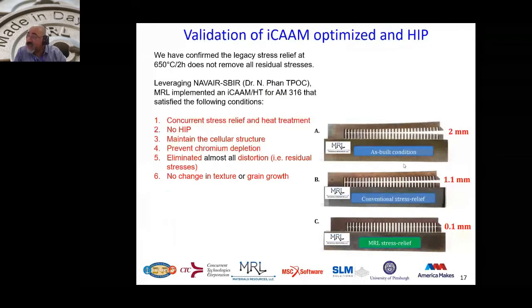What you will see in slide number 17 is comparing the as-built condition with the conventional stress relief process, and then with our stress relief approach. And you can see we wanted to demonstrate it in the standard cantilever. The heat treatment approach that we developed at MRL resulted in less than 0.1 millimeter distortion in the cantilever. And with that, we calibrated the models that we fed into SimuFact to be able to utilize this part for optimizing the build orientation, taking this heat treatment through the process.